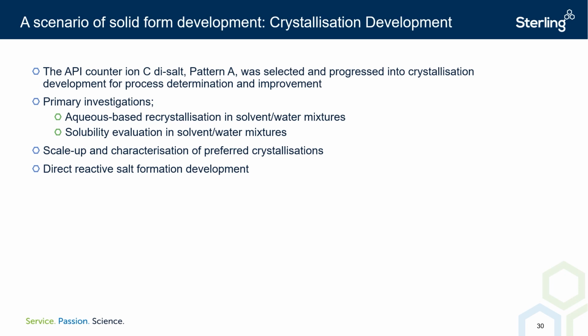With a range of suitable solvent-water mixtures selected, solubility evaluation was performed to understand the nature of the crystallization, with regards to solubility and subsequent control of the rate of crystallization. The most promising crystallization systems were scaled up, assessed further, and the isolated solids fully characterized, affording a proposed recrystallization